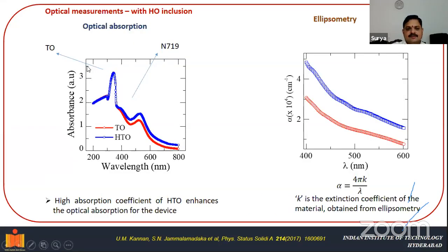We also tried to analyze with the optical absorption spectra. As soon as we added the holmium, the absorption of the device enhanced, because holmium has high optical properties. We also obtained lambda versus alpha, the absorption coefficient, where alpha is equal to 4 pi k by lambda, and we analyzed this using ellipsometry experiments. Here k is the extinction coefficient of the material obtained from ellipsometry. What we could see is that the absorption coefficient of holmium added titanium dioxide is higher in comparison with the parent titanium dioxide.